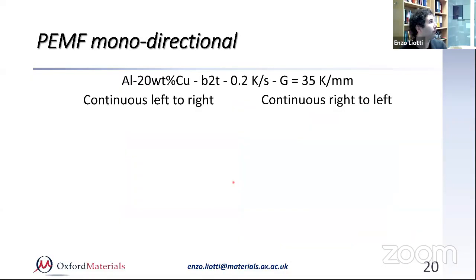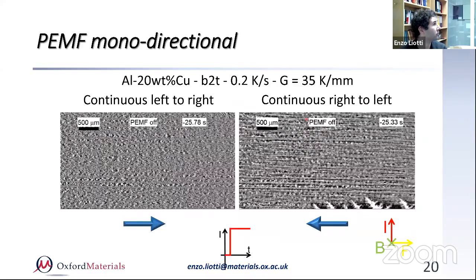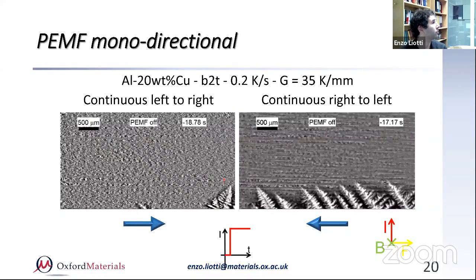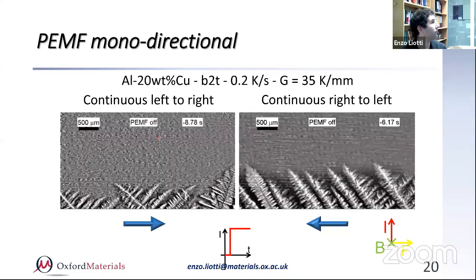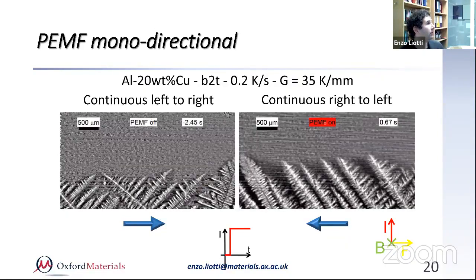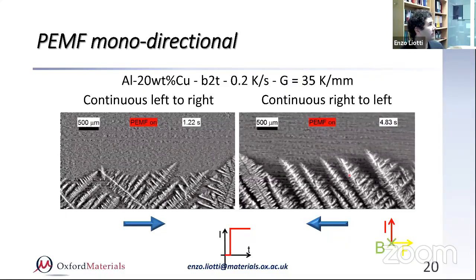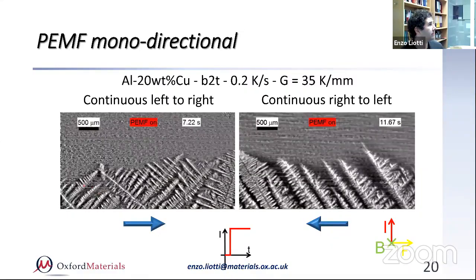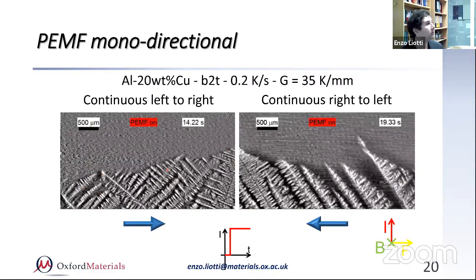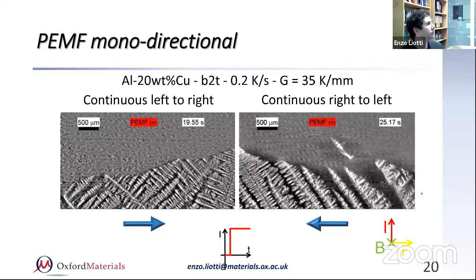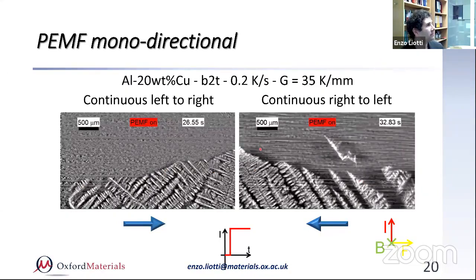So what you see here is an example of the growth of a columnar dendrite, where there is a continuous electromagnetic field. So you see the dendrite growing, right? At some point, the PEMF is still off, and at some point it will be turned on, and you will see that essentially this is pushing in this direction, and you see it's remelting this direction, and here is remelting here, right? And in this case, because it's continuous, it's almost a steady state.